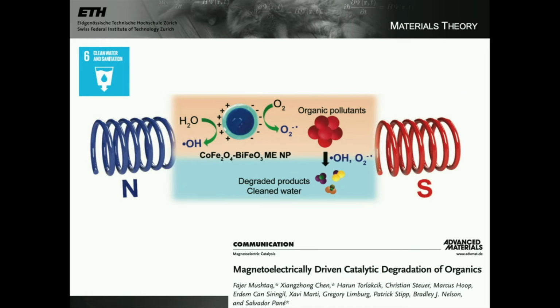And so water or oxygen will adsorb on these charges to screen the surface charges. Then with a magnetic field, or alternating magnetic field, the electric polarization is changed and the surface charge changes. This causes the molecules to dissociate and form radicals, which are then able to break down the organic pollutants. So it's kind of a similar mechanism to photocatalysis, except instead of the photo, with a magnetic field you're breaking down the water. So this is an extremely beautiful work, I think.